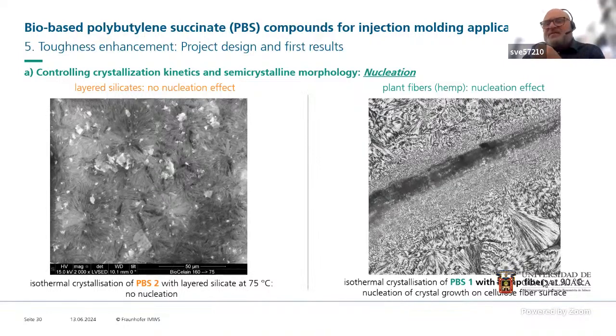That is the business of the Fraunhofer Institute in Halle. And another story is, why not do nucleation? Why can't we introduce nucleating agents to have a fine spherulitic texture? Of course, we can do that. You can see the picture over here. Here, it does not work. You can see that we have the spherulites that are not at all influenced by the filler we put in. So the spherulitic structures are not influenced by the filler, but on the other picture, that is an interesting story indeed. When you introduce, in this case, hemp fibers, this is cellulose hemp fiber material, then you can see that the spherulitic structure, or the crystalline structure, is growing.